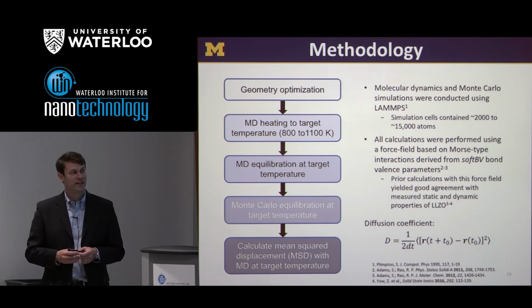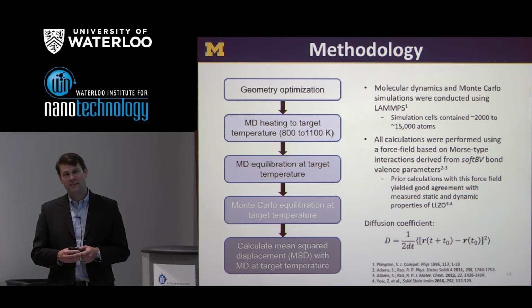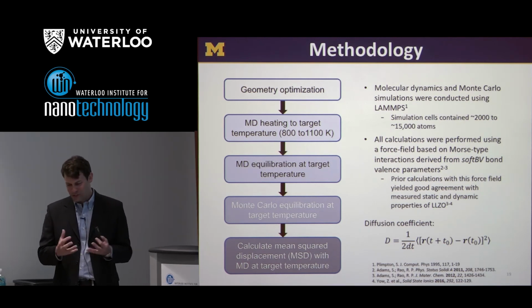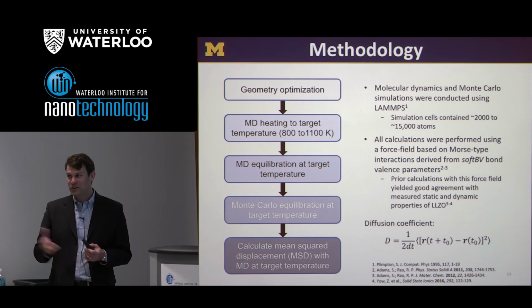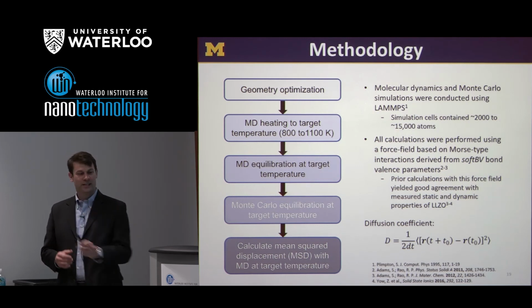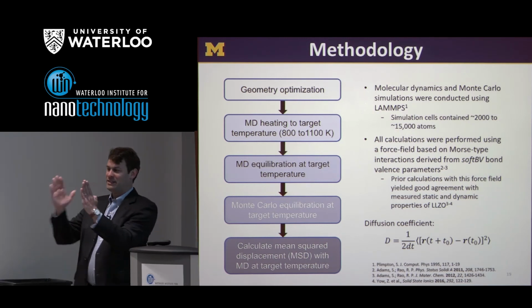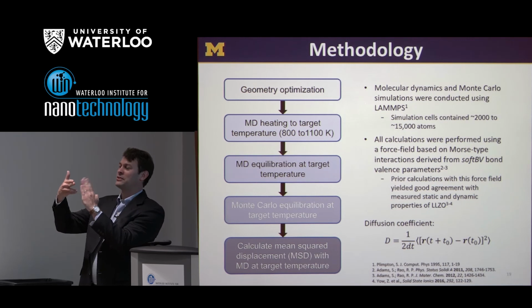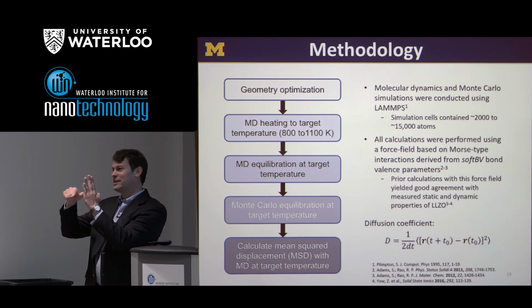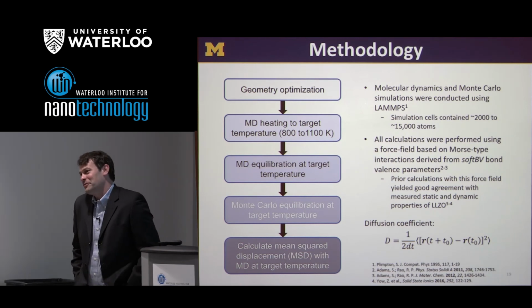I think there's an electrochemical reason, or a composition difference region, or a microstructural feature. Maybe there's some porosity there we don't know about that exists at that grain boundary junction. So if this is lithium metal, and I take my LLZO, imagine this is a grain boundary. If I put it up like that, maybe there's some void space here that results in the nucleation of those dendrites.